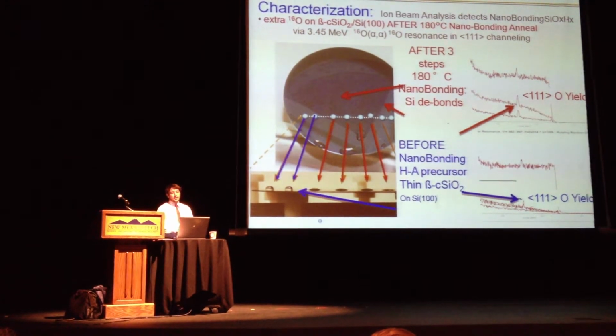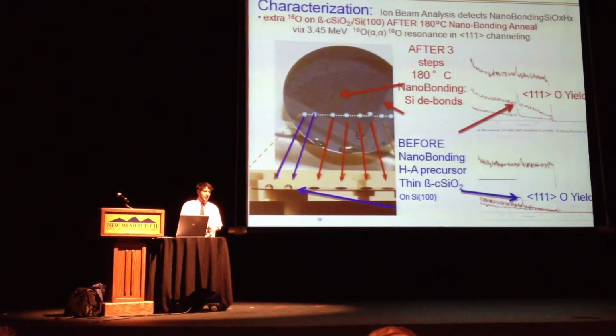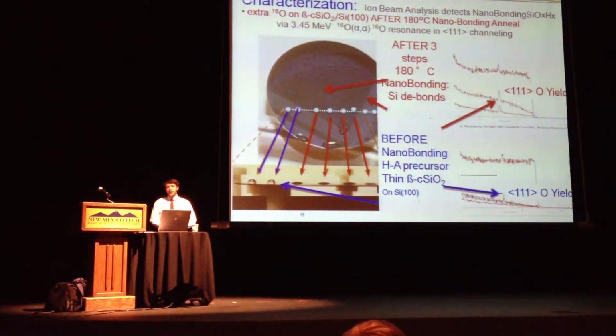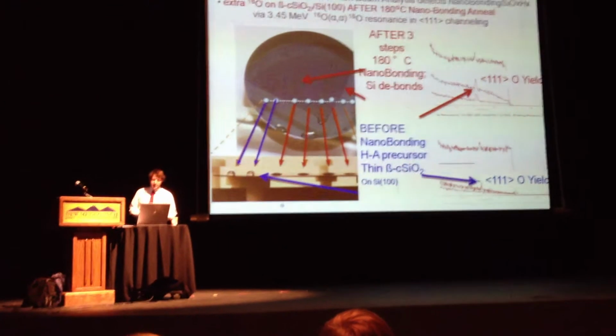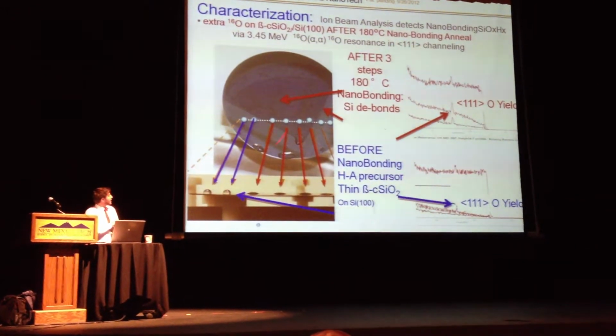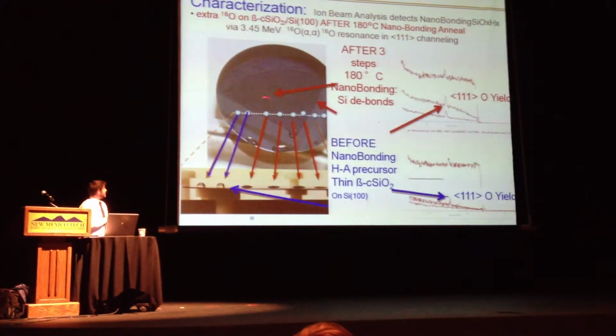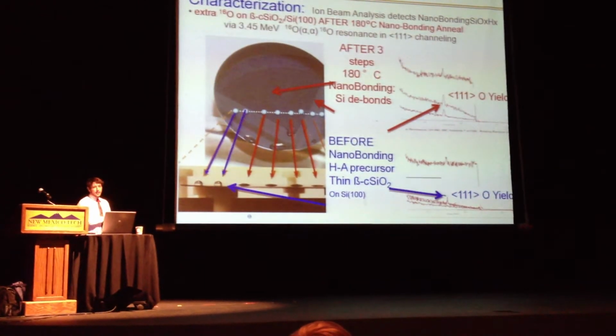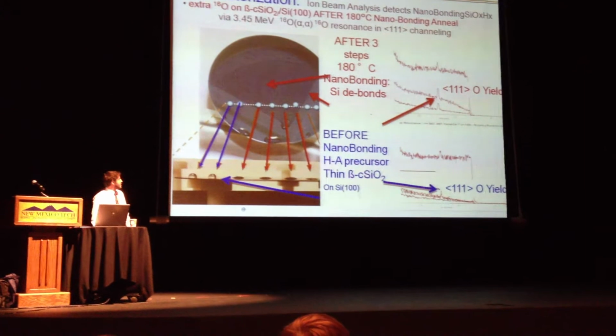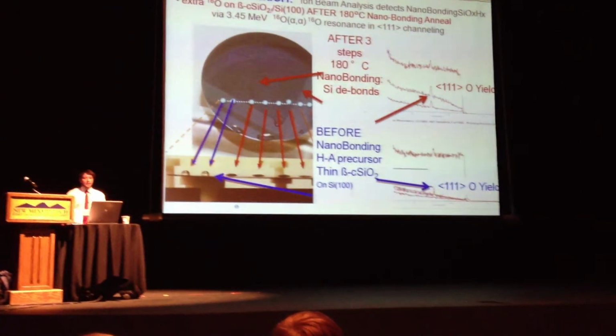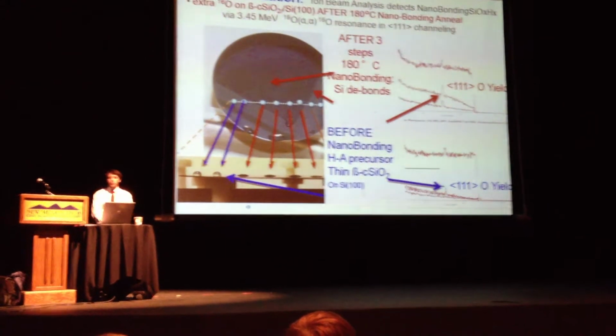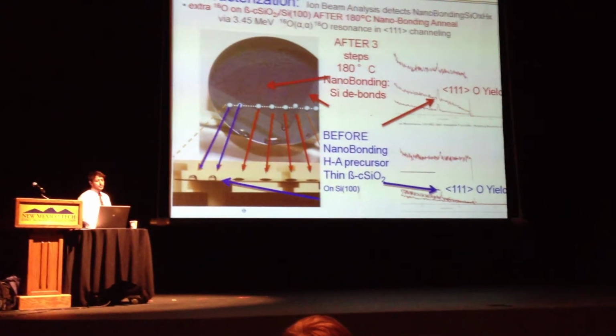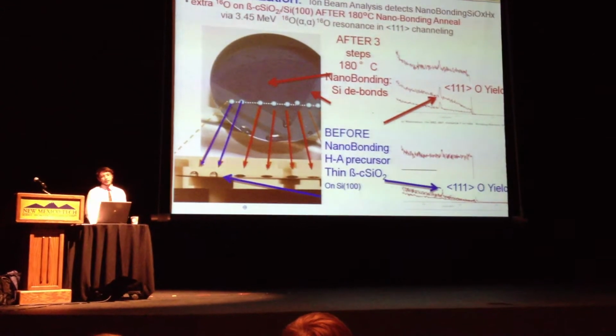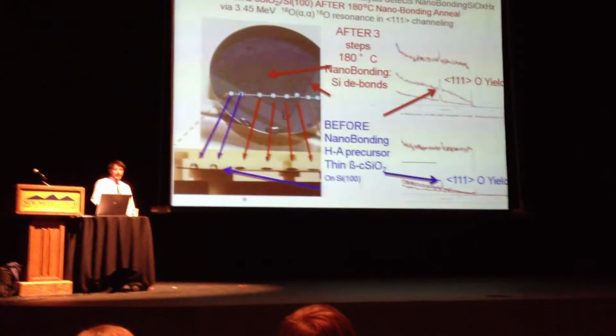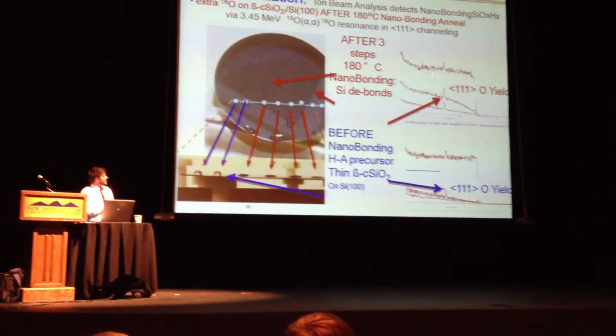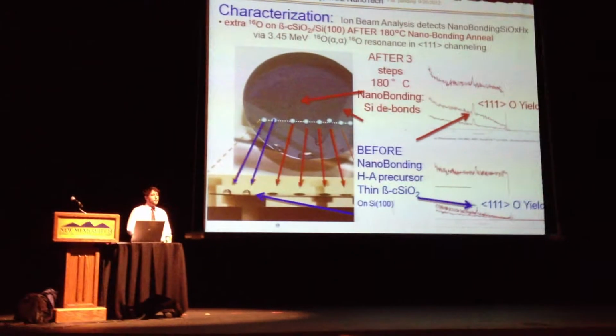And some examples of post-nanobonding and some evidence that we actually do have bonding aside from the contact. We see here higher roughness where we had a sample placed to be bonded, which you can tell by the hydrophilicity of the water there, as opposed to on just the annealed silicon. And then additionally, we would expect after ripping apart the wafers that we would see a higher oxygen yield on the silicon side due to the deposit of the oxide. And again, in our ion beam analysis of this, we see a higher oxygen yield on that wafer.